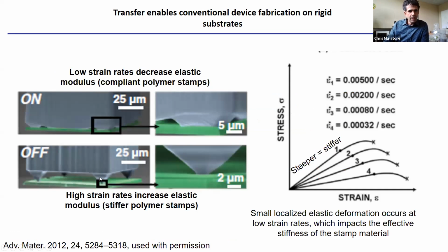So here are some nice images of a stamp that's being applied to, let's say, some ink. Let's say we want to pick this green thing up with our stamp. And so I can change the rate at which I strain the stamp. This stamp has these pyramids at the corners. You can see them here, right? So this is what it looks like initially. When I squish the stamp down, this is what it looks like. And I can control the rate at which I push that stamp down, and it's going to change the response of these features on the surface.